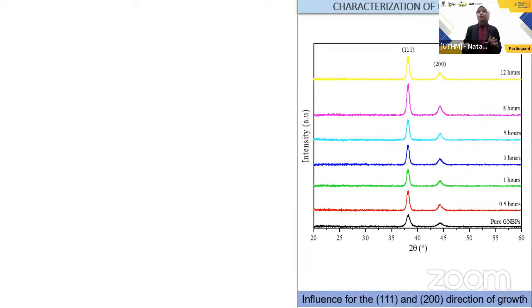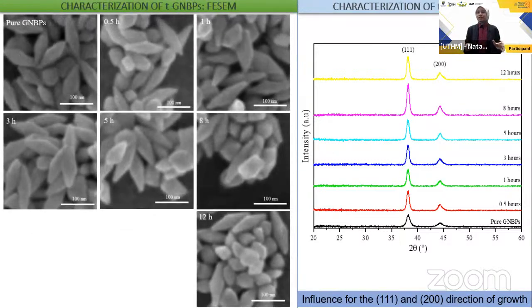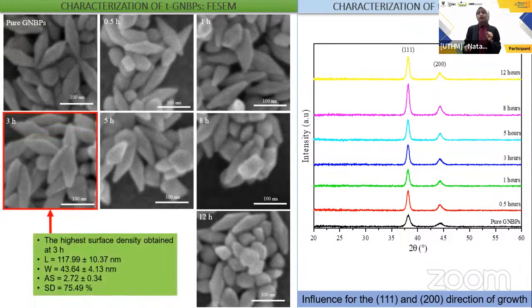Next, we have XRD. So this is the XRD pattern for T-GNBPS. We didn't see any additional peak here, as with GNBPS before and A-GNBPS before, right? This indicates the purity of the nanoparticle itself. But if we look clearly, the usage of thiol groups can influence the growth of the 111 and 200 planes. Next, FESEM. So these are the FESEM pictures of T-GNBPS. Based on this result, the highest surface density is obtained at 3 hours with a value of over 75%.